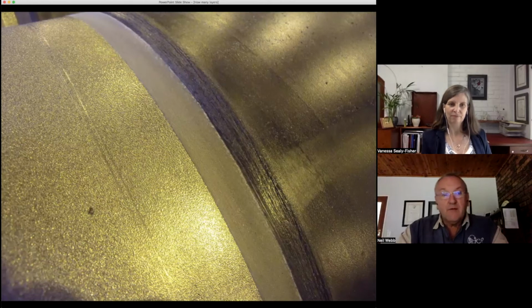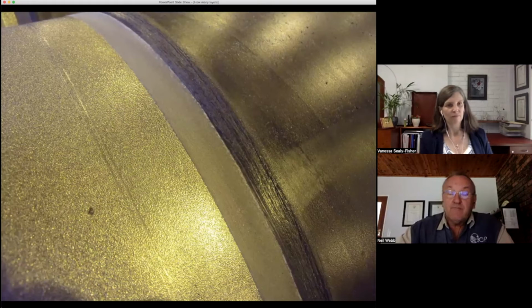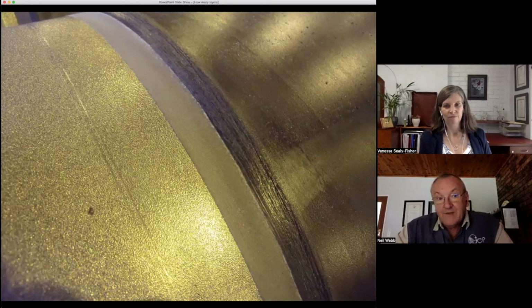And if the epoxy layer underneath is not man enough for the job, we'll end up with disbondment of polyethylene, of the 3LPE system, and effectively a loose bonded sleeve. Now, it's still pretty tight around the pipe, but there may well be water underneath it. It's not a problem unless there is a defect in the coating, mechanical damage, in other words, or a failed field joint or something like that, that allows electrolyte to be transferred between the space underneath the coating and the external environment. And when that happens, then you get underfilm corrosion underneath the polyethylene.